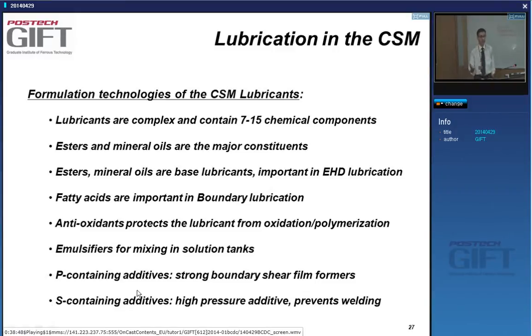And those are not organic molecules. They're added to form very strong films at the surface. The phosphorus-containing additives form very strong films that cannot easily be sheared. And the sulfur-containing additives are very resistant to high pressures, and they prevent welding, cold welding. We'll see where the cold welding occurs.